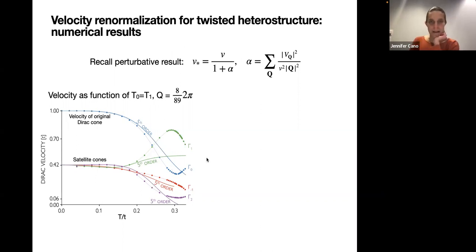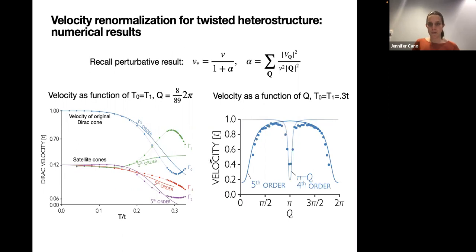that we can change the velocity of the Dirac cone by applying a superlattice potential. We can also plot this in a different way, which is to keep the potential strength the same, but change the wave vector or the length scale. Same thing: each one of these dots is a different numerical simulation as we're changing the wave vector Q, and the lines are showing our perturbation theory. They trace out each other pretty well. Again, we can change the Dirac cone velocity at least down to half of its original value by changing the length scale of this potential. It seems like this plot could keep going down even more, but it became numerically unfeasible to consider larger system size than this. So I think that this platform offers us a great degree of tunability in changing the Dirac cone velocity.